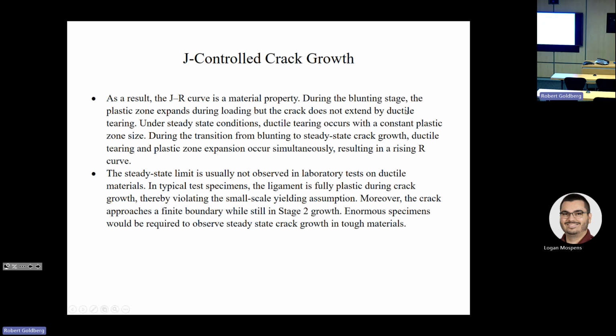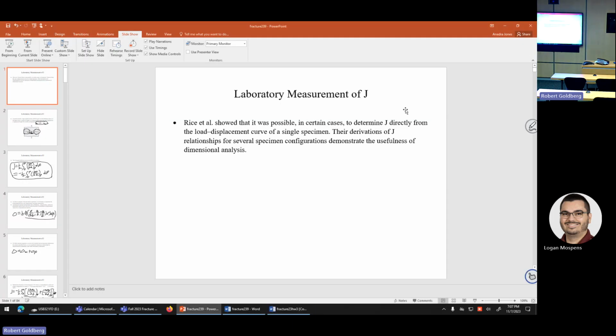Now in laboratory tests, the steady state limit is usually not observed because in typical test specimens, the ligament is fully plastic during crack growth. Therefore, you don't have small scale yielding, which violates the assumptions. And the crack also approaches the finite boundary while still in stage 2 growth. So you would need really big specimens to observe steady state crack growth in tough materials. So that's what we have. This is our introduction to plastic fracture mechanics.